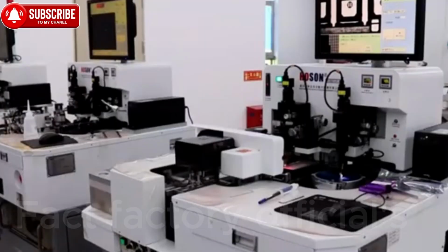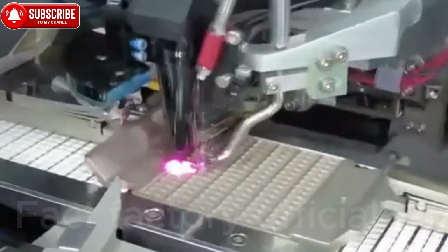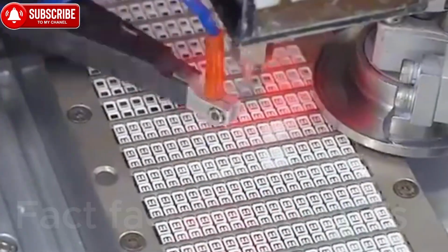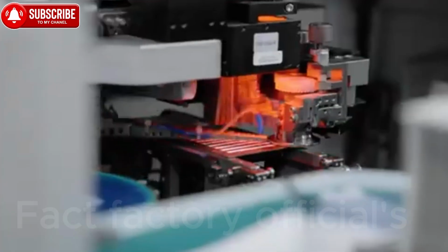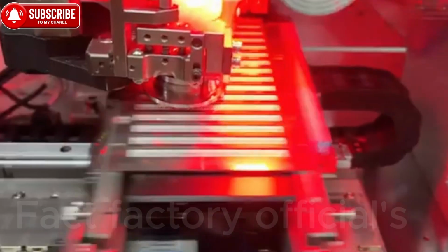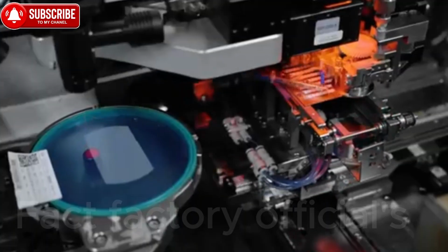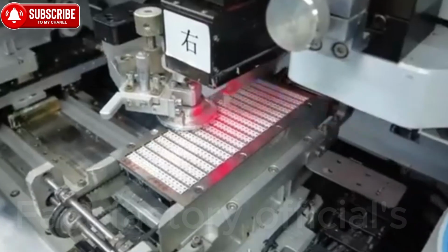The expanded film carrying the separated chips is fed into the machine. Industrial vision cameras scan the entire surface automatically, identifying the exact coordinates of each chip as well as the metal pads on the lead frame. This allows the system to calculate positional offsets within just a few micrometers, ensuring that every chip is placed with extreme precision. The robotic arm operates at near instantaneous speed: pick up, rotate, align, and place, each cycle taking fractions of a millisecond. A gentle downward force is applied to spread the adhesive evenly, preventing air bubbles and ensuring the chip remains perfectly level. Precision at this stage is critical.